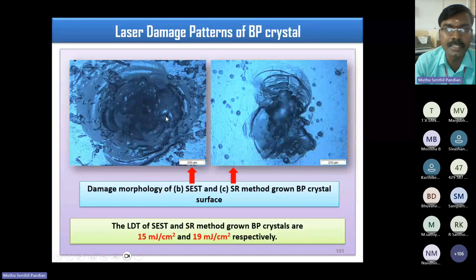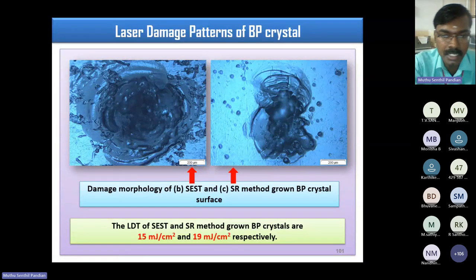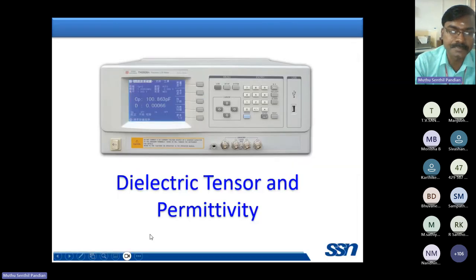This is one more example, the world's longest benzophenone single crystal, and we cut it and made it into a very thin plate, and we checked the laser damage threshold value for the conventional and SR method grown benzophenone single crystal. Because of the higher dislocation density and large number of solvent inclusions, it is 15 millijoule per centimeter squared for the conventional method grown benzophenone single crystal. But in the case of the SR method grown crystal, as I mentioned, with no solvent inclusion and higher crystalline perfection, the laser damage threshold value of this SR grown crystal is superior compared to the conventional method grown crystal.